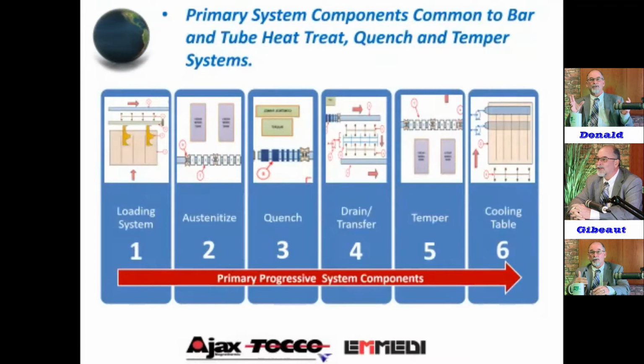A drain and transfer table, that's a table that usually is on an angle, and we'll show you pictures of it, but it also has a forced air side to it that blows down the ID of the tube, designed to get all the quench water out, because we have quite a volume, the largest volume aggressive quench in the world that we know of. And so this drain and transfer is a critical element. It also allows us to put in a buffer for metallurgical as-quenched samples.